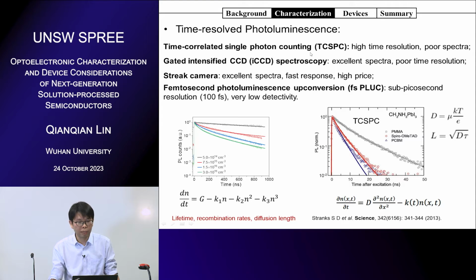It has been done a lot with TRPL, but this technique also has some problems. It normally gives you the minority carrier lifetime of the semiconductor. If you have an intrinsic semiconductor, it doesn't matter. It gives you a kind of lifetime. But if you have a slightly doped semiconductor, it will give you more direct information about the minority carriers. Because if you have 50 electrons and 100 holes, then 50 electrons may combine with 50 holes and emit photons. All your measured signal is the emitted photons. So how about the other 50 holes? You cannot get direct information from TRPL.